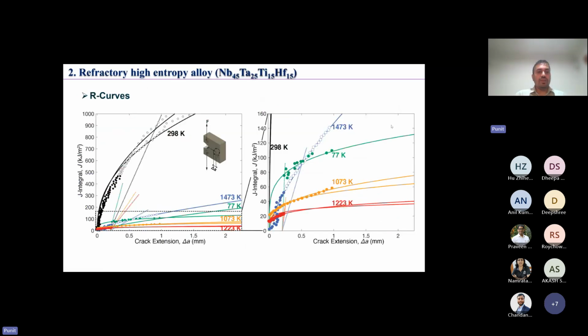And when we did a fracture resistance evaluation, the R curve evaluation of this material, the challenge was trying to get a valid fracture toughness, because this material shows plasticity even at higher temperature. We had to use the J method even at high temperature, and that's a really challenging task. Even doing a J test at room temperature is challenging, but we had to do the J test at very high temperature.